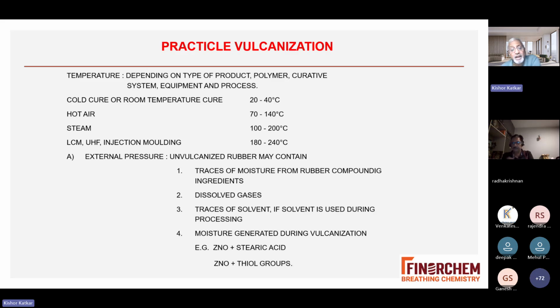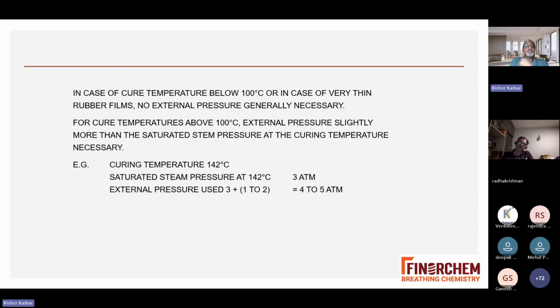Moisture is generated during the vulcanization reaction of zinc oxide and stearic acid, and of zinc oxide and thiol groups. This moisture becomes part of the rubber compound. If it remains there and you don't apply pressure during vulcanization, you will find bubbles in the vulcanizing rubber.